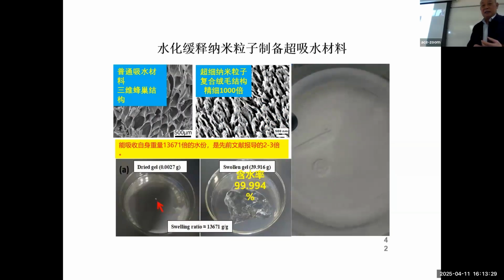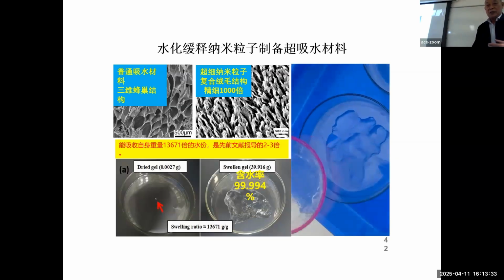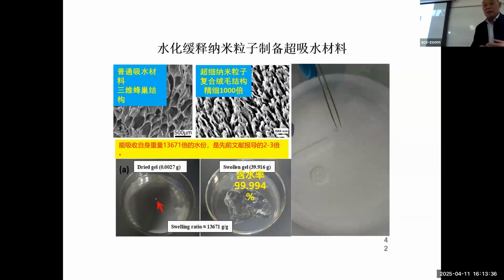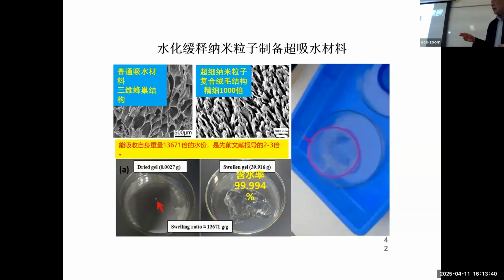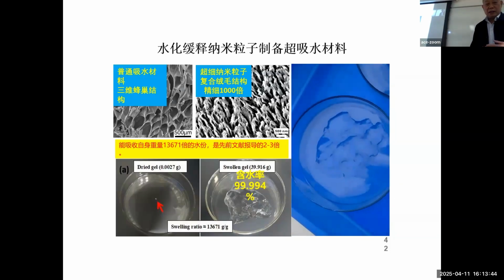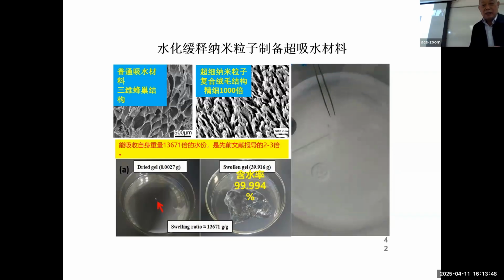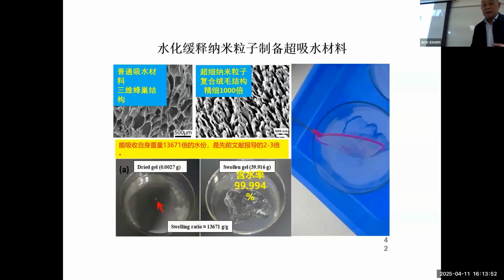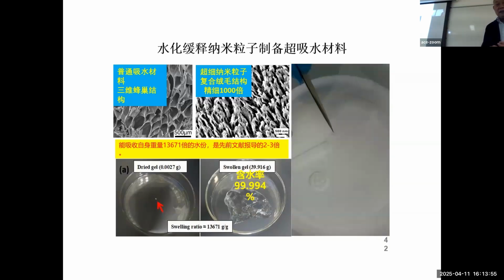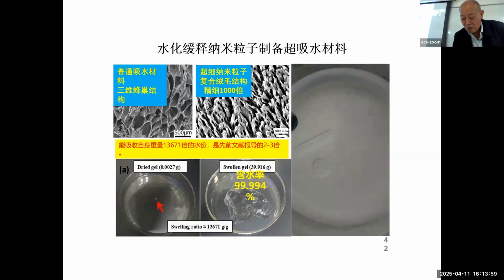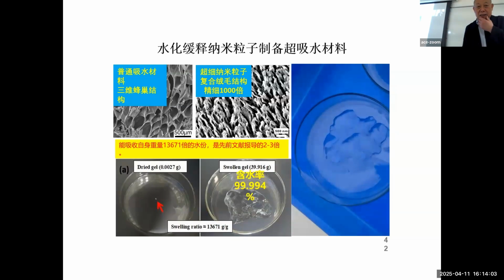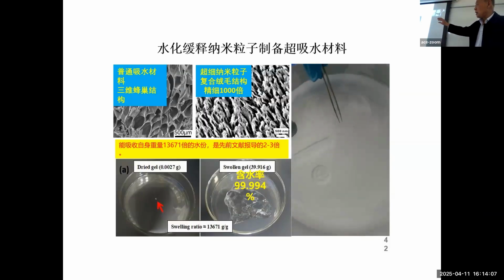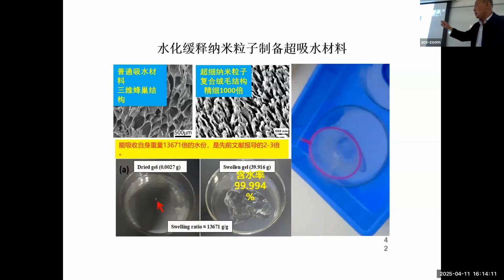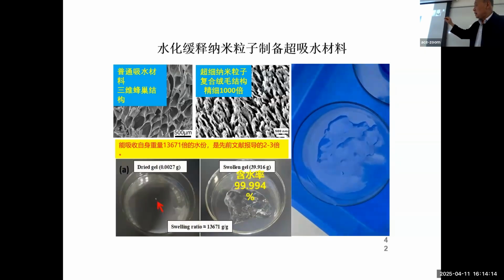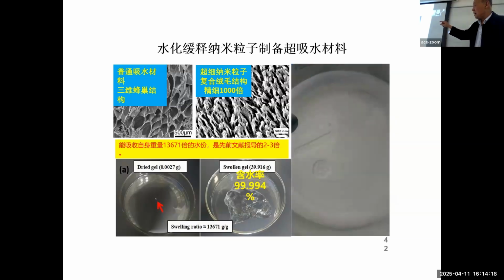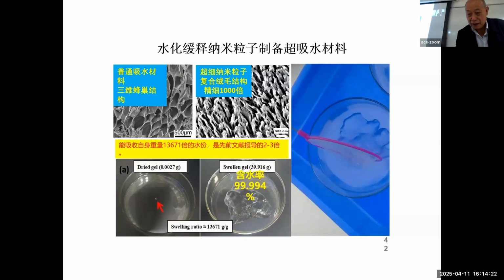And another, okay, we use this hydrogel to produce this kind of super absorption material. So the highest absorption for the hydrogel we produce with this nanoparticle is 13,000. So that is the highest we found in the literature. That's about 2 or 3 times what was reported. Okay. So why can it have this? Because in the microstructure you can see they have this very special kind of valley and something like hair growing on it. So that helps the absorption.